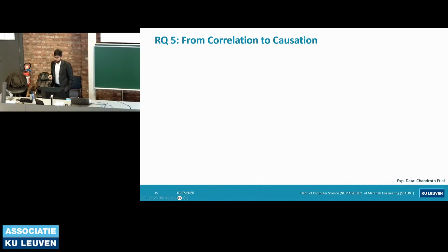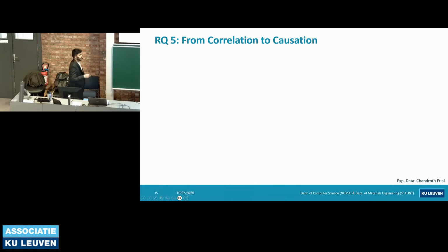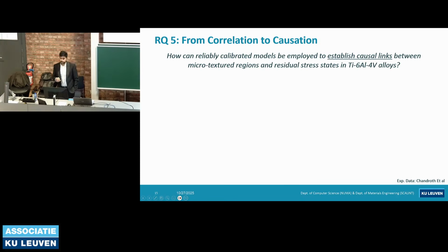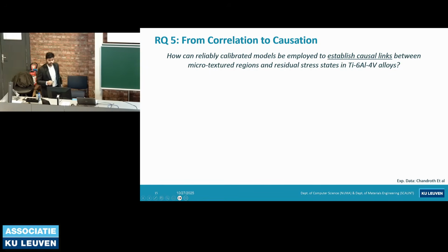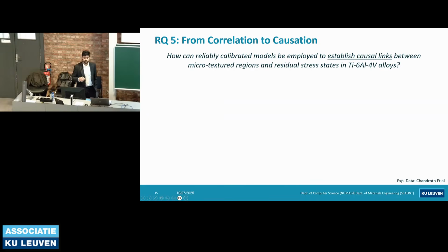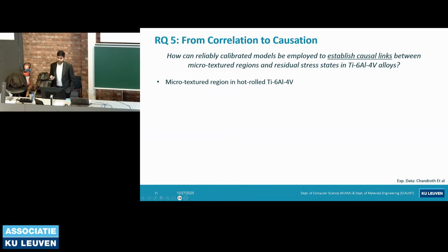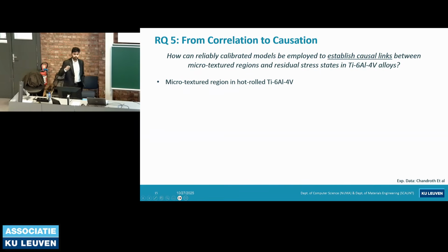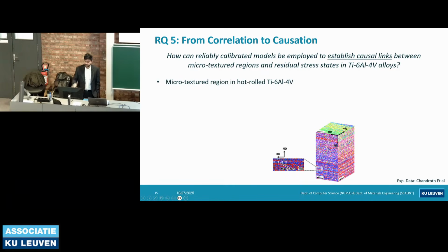Now, using this calibration, using these reliable parameters, we can actually look at the trends that we see in the experiments, whether they translate to just a correlation, or whether there is a cause for seeing those trends. So the last research question asked: how can reliably calibrated models be employed to establish a causal linkage between micro-textured regions, which are seen in titanium, and residual stresses in Ti64 alloy? It is often seen in titanium that after hot rolling, it has micro-texture regions of elastically stiff and elastically compliant grains, as you could see here.